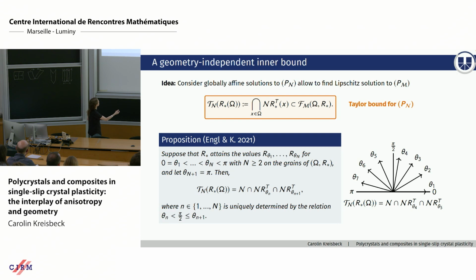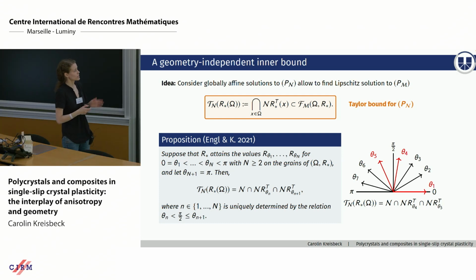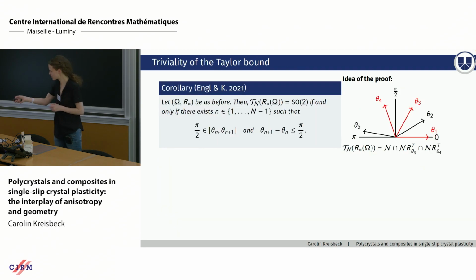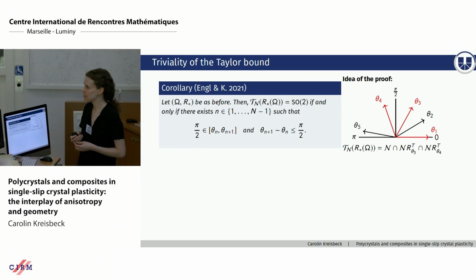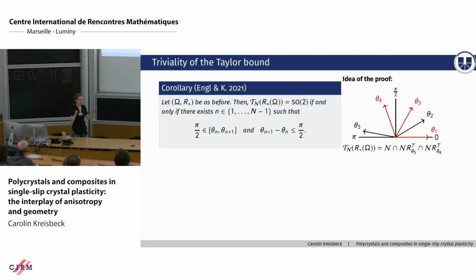So to calculate the Taylor bound associated with these orientation angles, it's just enough to take these red ones here. So theta 4 and theta 5 are closest to pi over 2. Okay, the calculation behind that, I have to say, is not really pretty to put on a slide. So instead, I'll show you just a corollary, which helps us to characterize the cases when the Taylor bound is actually trivial. Trivial means it's equal to SO2. And the criterion here is that the 2 angles that frame pi over 2 are at most pi over 2 apart. And the proof idea is really not hard and easy to see in one single picture.